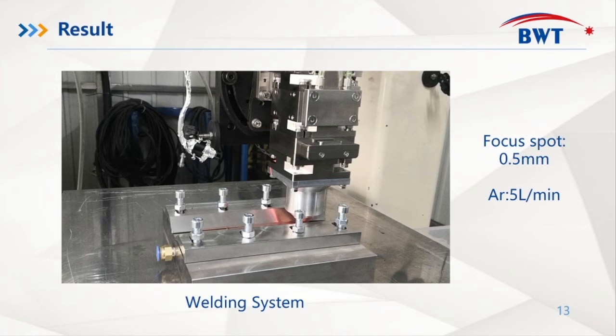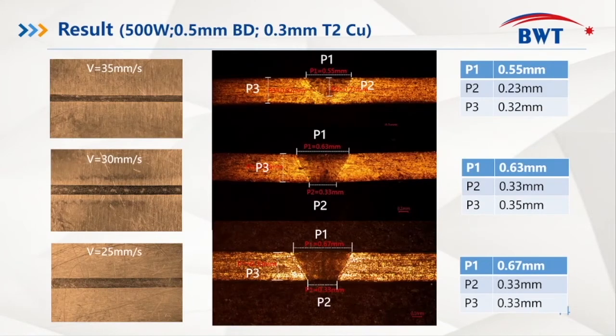Argon is used during the welding process. We use 500 watts power to weld 0.3 mm red copper sheet at different speeds, and the speed of 30 mm per second can penetrate. The width of the weld bead on the top surface is 0.63 mm. The bottom width of the weld bead is 0.33 mm, and the actual thickness of the copper sheet is 0.35 mm.